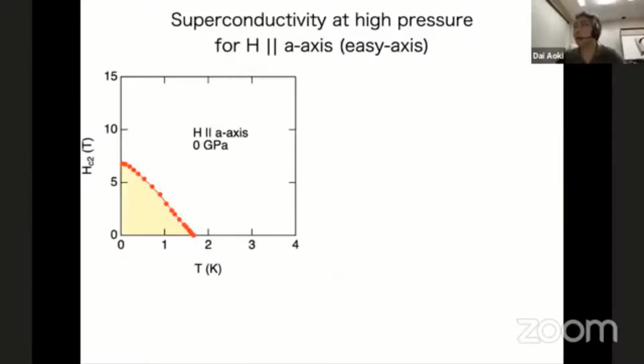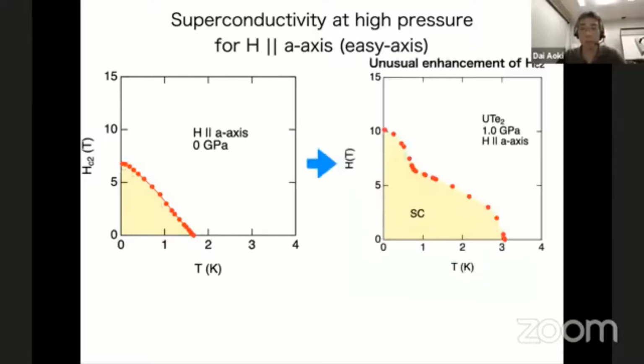Okay, so now I want to show you the results for the A-axis. This is the easy axis. You may think it's not so interesting, but in fact it's a very interesting case. The A-axis at ambient pressure is like this, but applying pressure, in the resistivity curve we found this kind of unusual HC2 curve, the bump.